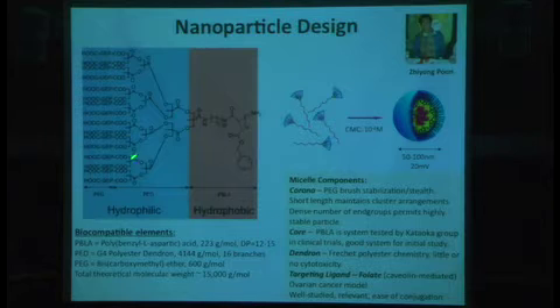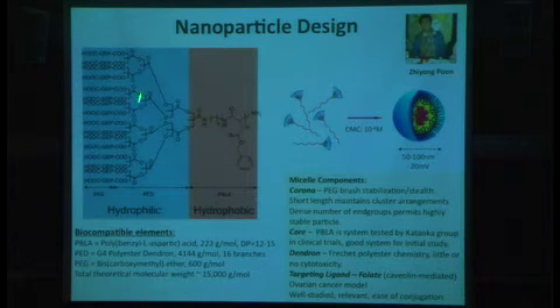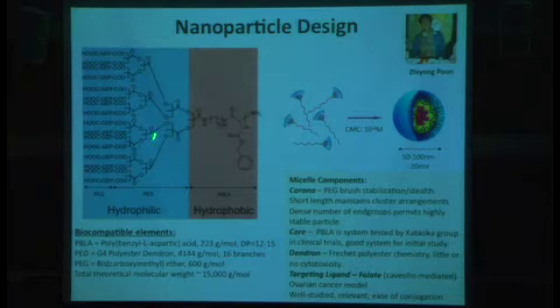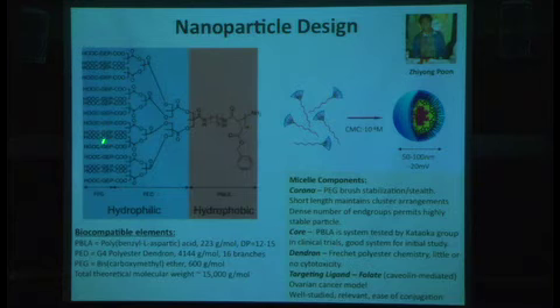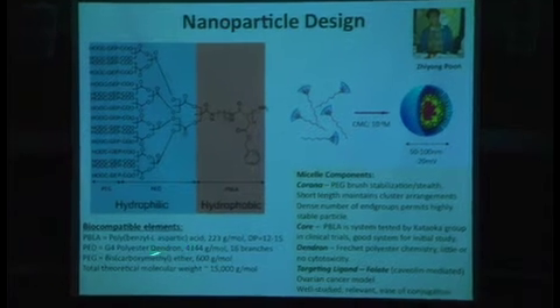We actually initiate this with a dendron. This is a polyester dendron. It has this very systematic branching architecture. And at the end groups, we have 16 of these end groups. We have polyethylene glycol, fairly low molecular weight, 600 grams per mole, and we can attach ligands via this carboxylic acid group at the end.